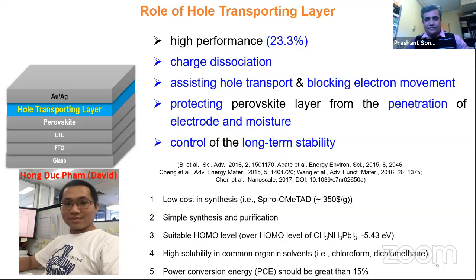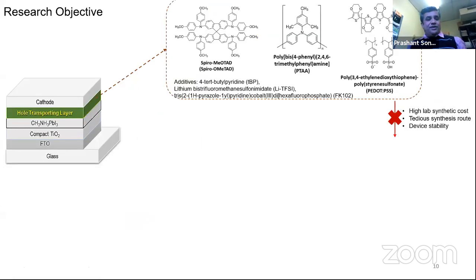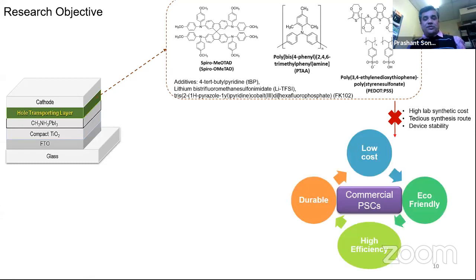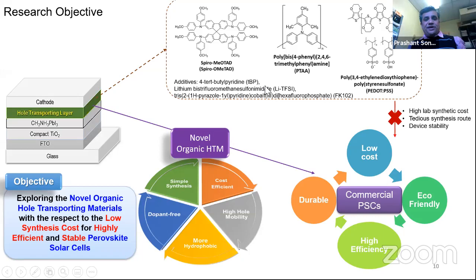So looking at the various hole transporting materials people are using, mainly I mentioned spiro-OMeTAD. Whenever people use it, they usually add additives called tertiary butylpyridine, as well as a lithium based trifluoromethane sulfonamide. Because of the addition of those two additives, the conductivity of spiro-OMeTAD gets high, and that is what makes it a better hole transporting layer. But again, look at those materials. Lithium is also a salt by nature. Your perovskite is also an organometallic halide, a bit of an ionic compound. So you are making the whole system very vulnerable to moisture.